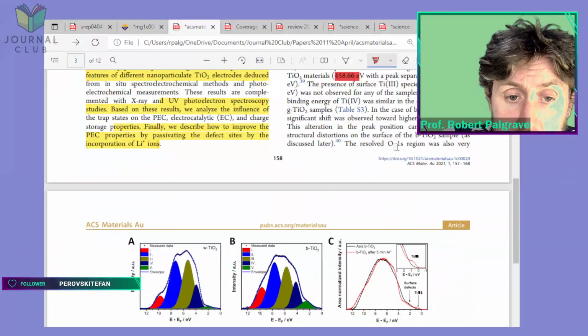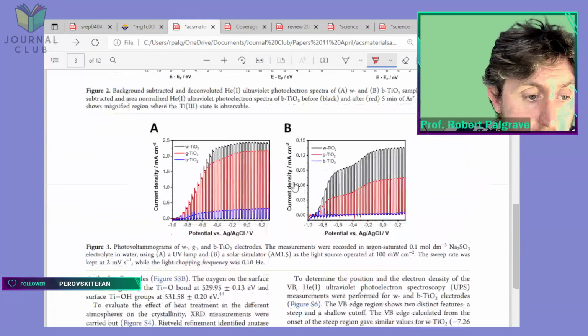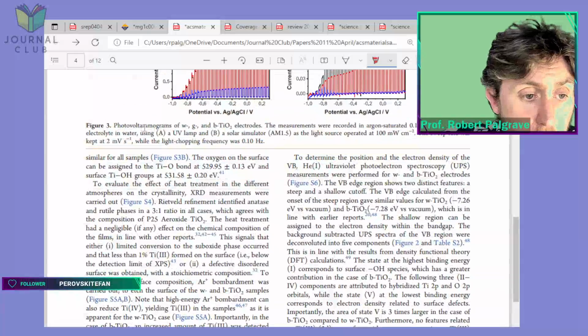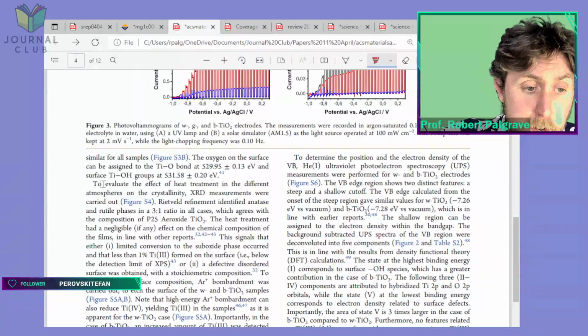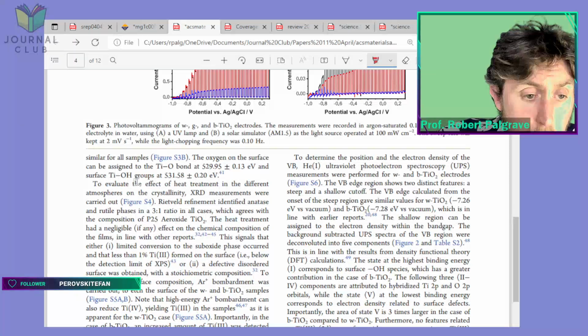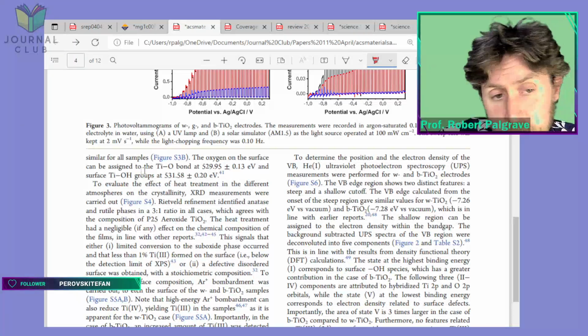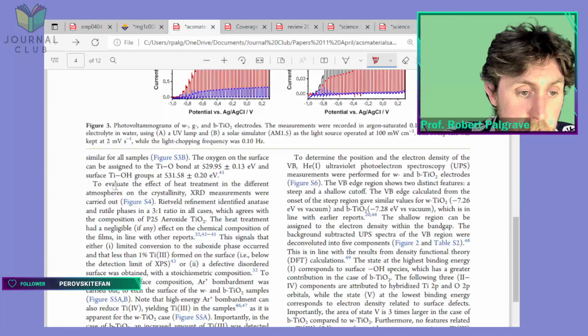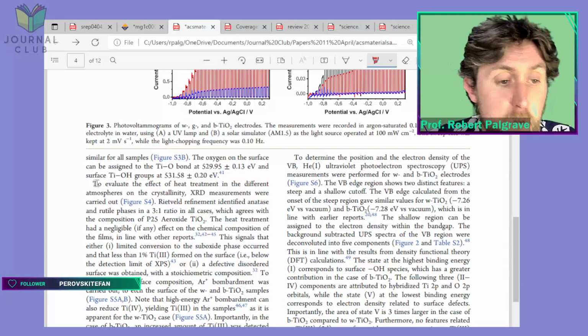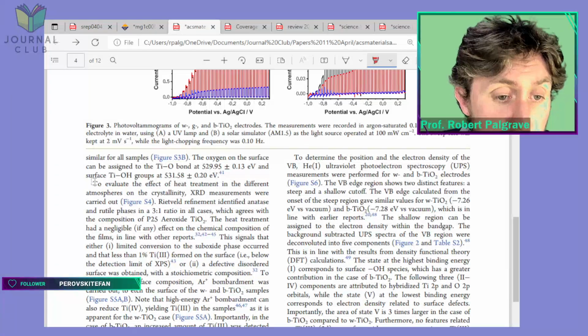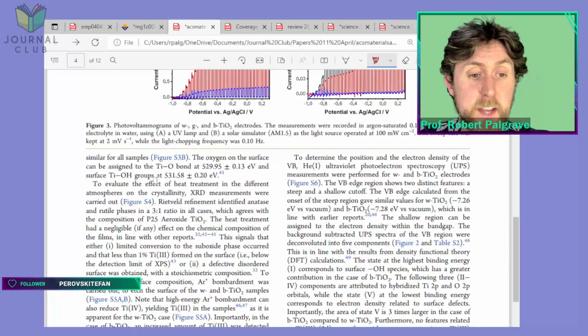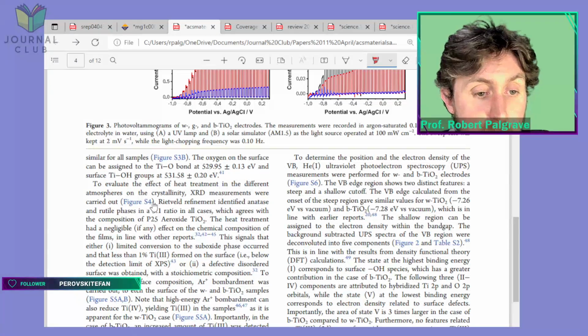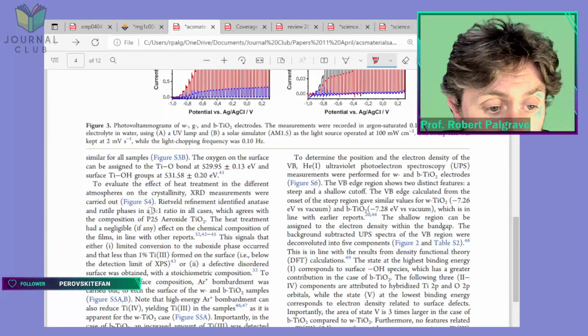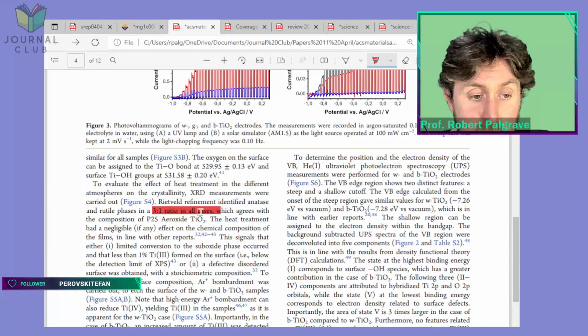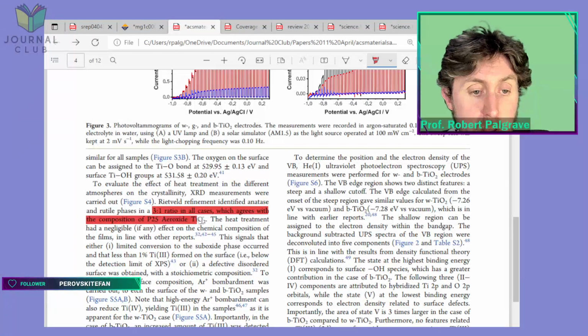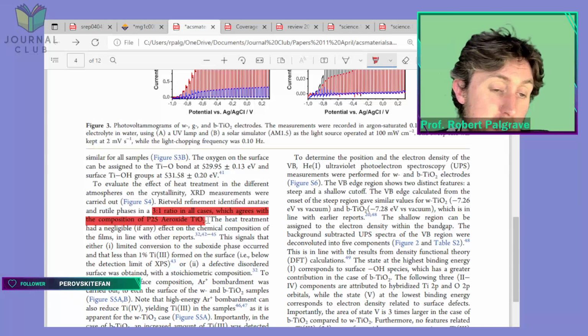The oxygen 1s resolved region was also very similar for all samples, and I mentioned that. To observe, so they talk about the presence of hydroxide groups as they mentioned in the supporting information. To evaluate the effect of heat treatment in different atmospheres on crystallinity, XRD measurements were carried out. Rietveld refinement identified anatase and rutile phases in a 3:1 ratio in all cases, which agrees with the composition of P25 TiO2. Well, that's lucky, isn't it?